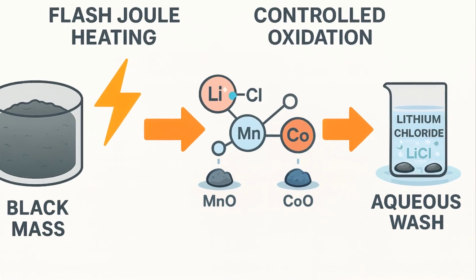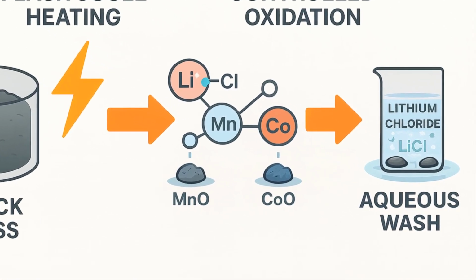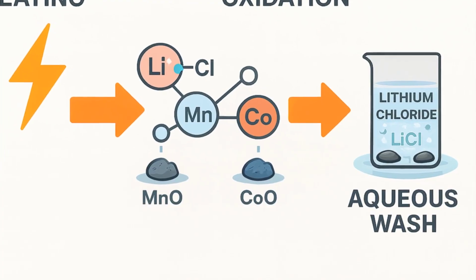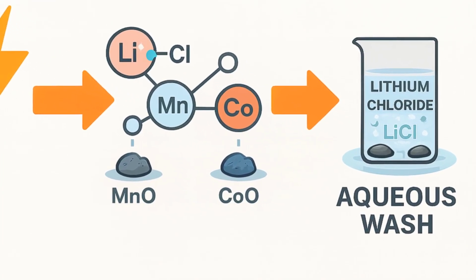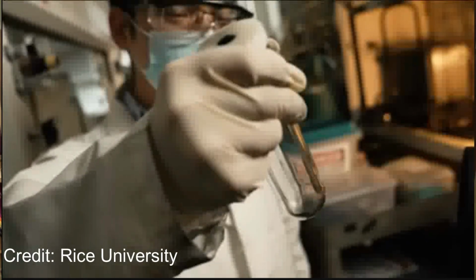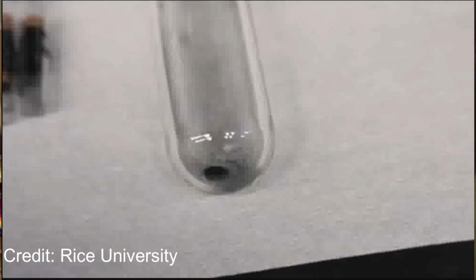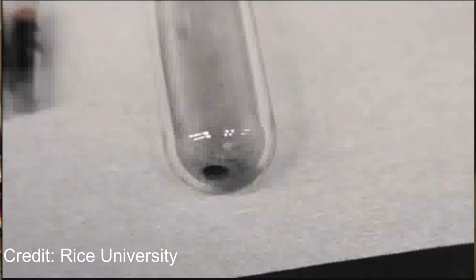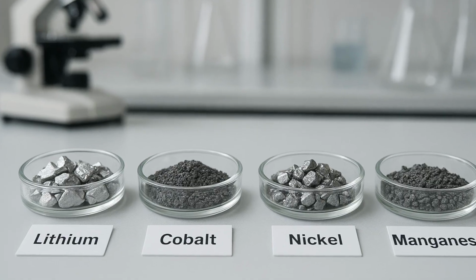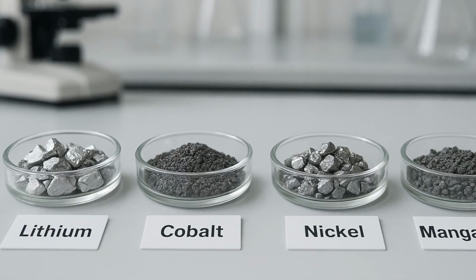Step 2, oxidation. After the flash step, a controlled oxidation converts the transition metal chlorides into oxides while leaving lithium as lithium chloride. Because lithium chloride dissolves easily in water and many metal oxides don't, the simple aqueous wash pulls out the lithium, separating it from nickel, cobalt, manganese, and the graphite anode material.